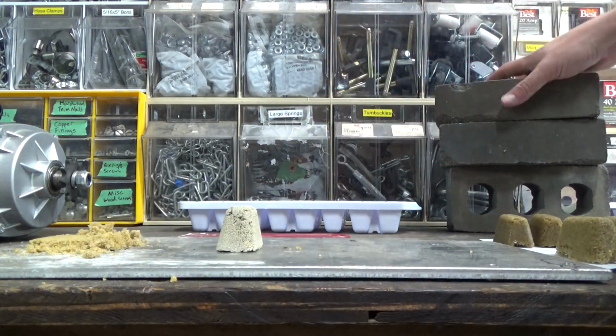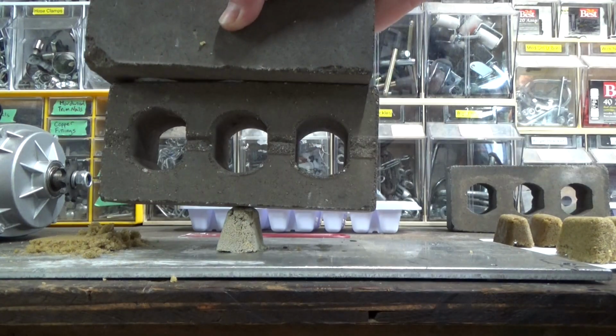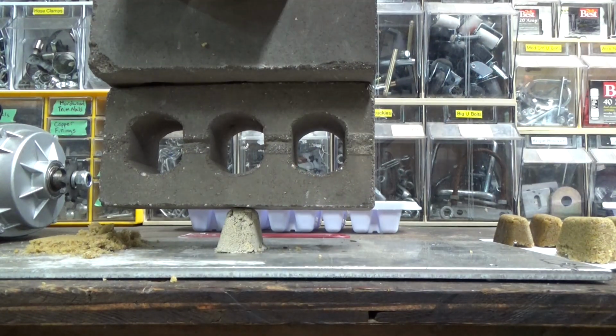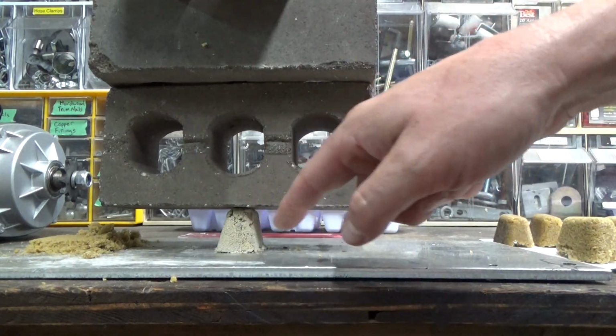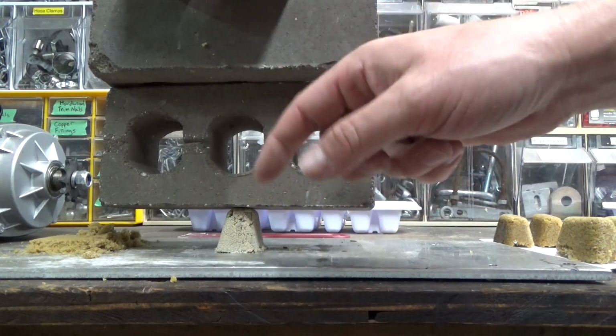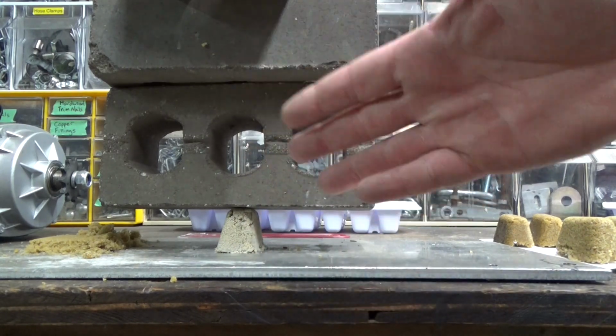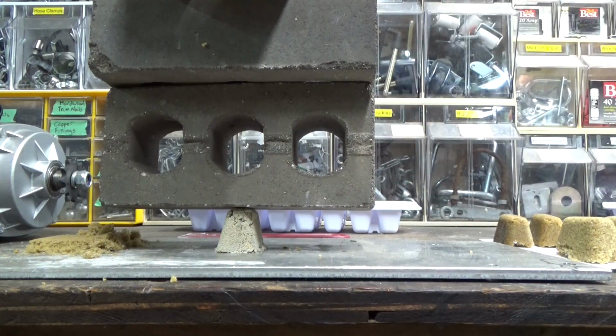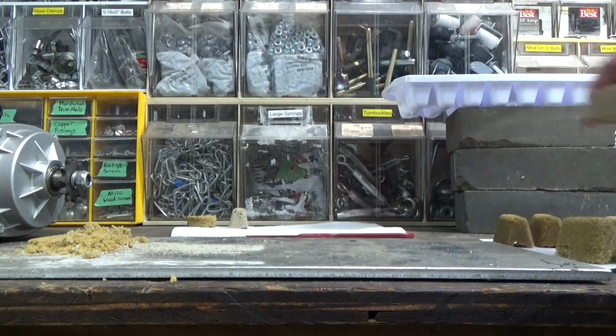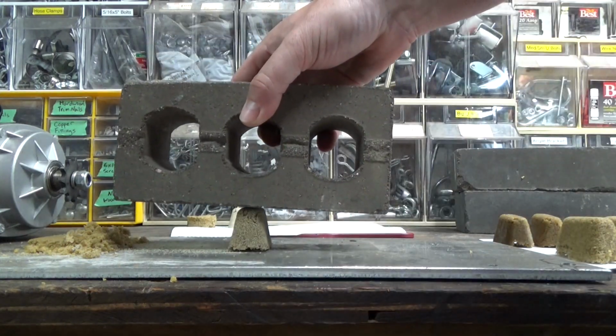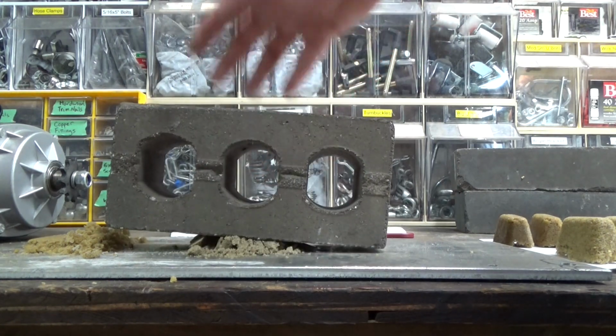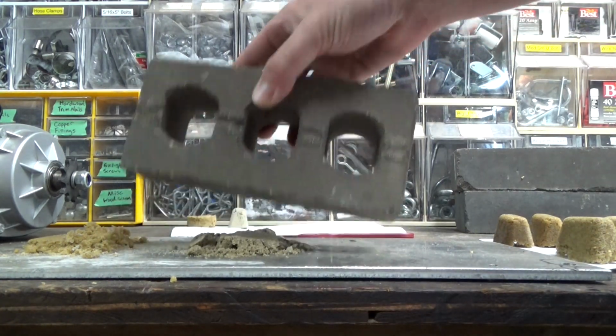Portland cement and sand. And it is supporting 3 bricks. We've had a little bit of sand loss around the bottom because there's some sharp edges from the mold, but as a whole it is holding up 3 bricks. Next up is high strength mortar. 0 bricks, at least in the ratio that I used.